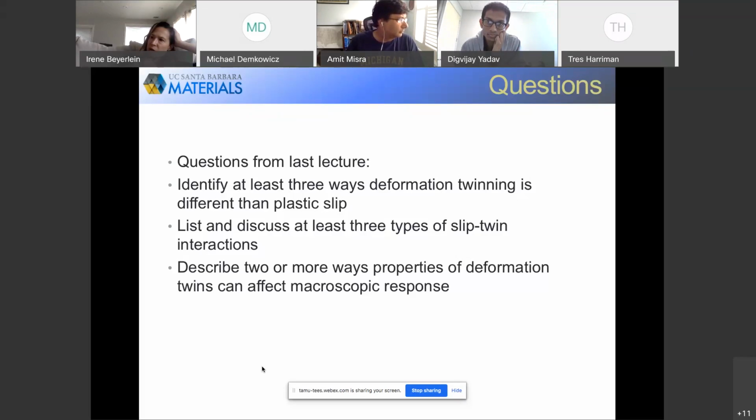I think so, since it doesn't involve diffusional processes. It does involve some amount of atomic shuffling. Yes. And that's the case in all twins in HCP. Yes. And the amount of atomic shuffling varies with different slip modes. And that does affect strongly the kinetics.